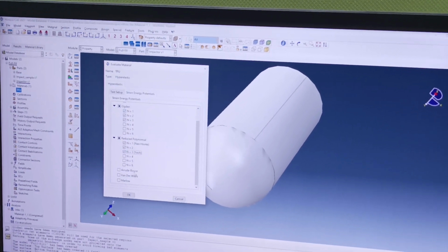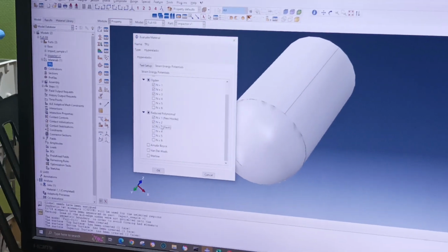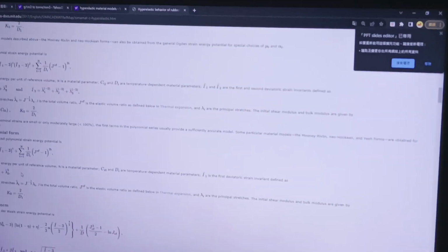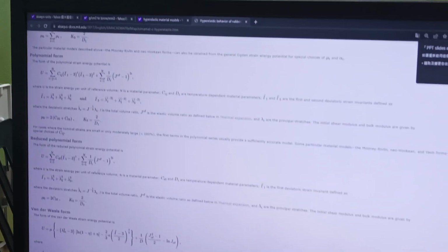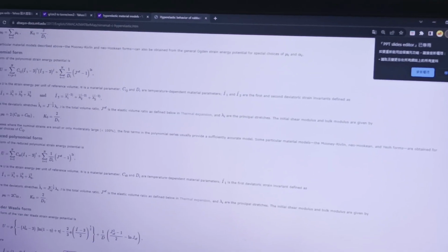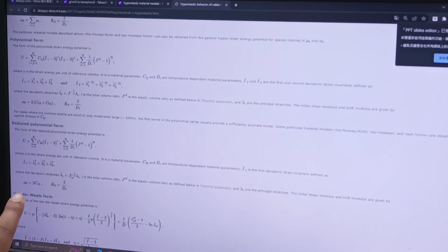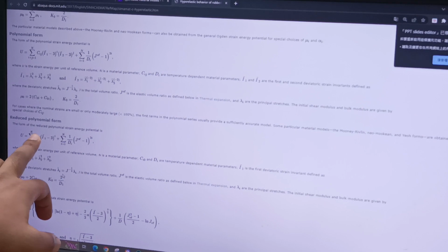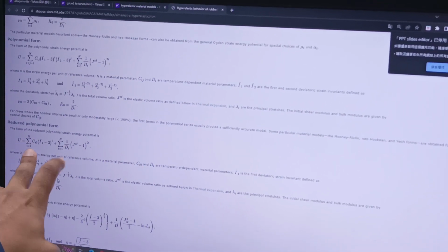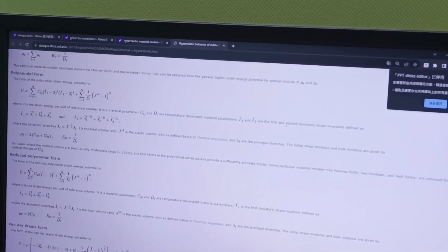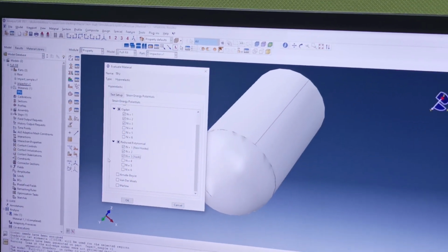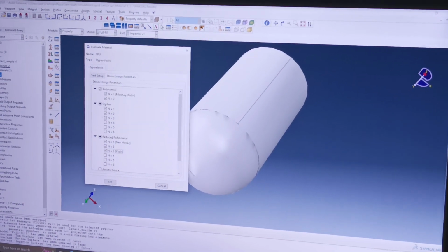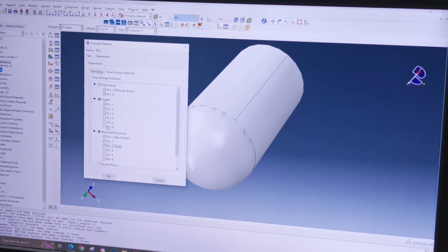So usually this represents different equations. And the higher the number n, the more complex the equation. It will not necessarily describe the TPU more precisely, but it becomes more complex because you see it's a summation over n. That means it will have terms 1, 2, 3. So the more terms the equation has, the more complex it becomes, and it's difficult to match. From my experience, I just take up to 3rd order. More than that is always unstable.